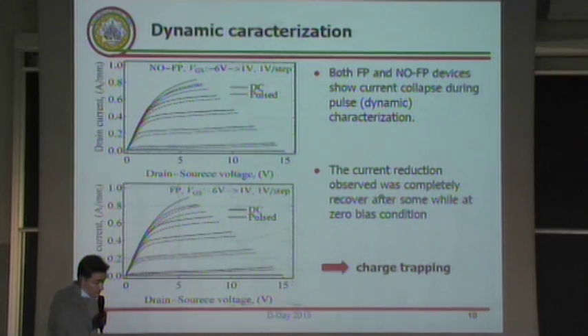What we did first was to measure the dynamic and static characteristics of the device. As you can see, in both no-field-plate and field-plate devices, we observe a degradation of the dynamic performance of the device. The current, when the characteristics are measured dynamically or using short pulses, is lower than that observed in static characterization. And we see that this degradation was not persistent, but was recovered after a while at zero bias. That was a clear indication of the presence of charge trapping.